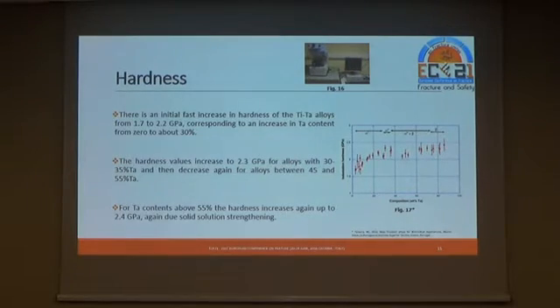The hardness. There is an initial fast increase in hardness of the titanium tantalum alloys from 1.7 to 2.2 gigapascal, due to an increase in tantalum content from 0 to about 30%. The hardness values increase to 2.3 gigapascal for alloys with 30-35% of tantalum, and then decrease again for alloys between 45 and 55%. For tantalum contents above 55%, the hardness increases again up to 2.4 gigapascal, again with solid solution strengthening.